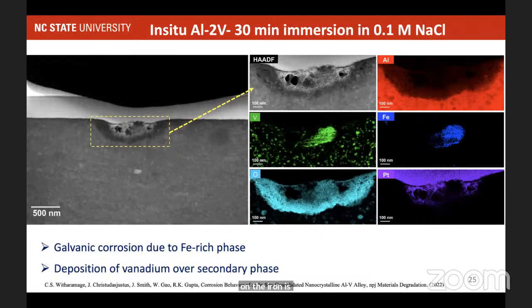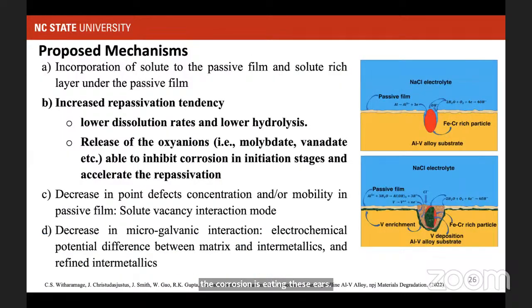So if you don't have enough cathodic activity, you cannot have this critical pit solution which is needed for the pit growth. So you can have lots of pits forming, but they don't grow because this vanadium could redeposit on those cathodic particles and shut down the corrosion as it initiates. So that helps in understanding what could be our future alloy design strategies.